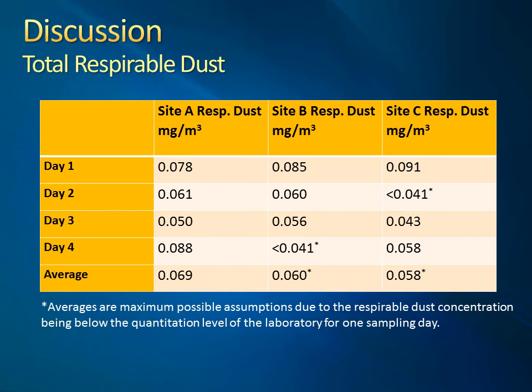The total respirable dust was collected and would have been used to determine the PELs of the silica forms if necessary. Instead, the respirable dust is the only measurable analyte that can be used to determine if the sampling area and location of the sampling trees have any effect on exposure. Site A samples, which were closest to the crucible, were all quantifiable, while both Site B and Site C had at least one day where the respirable dust concentrations were below the level of quantitation of the laboratory. In this case, we're going to make the assumption of the maximum possible respirable dust concentration for those 2 days.